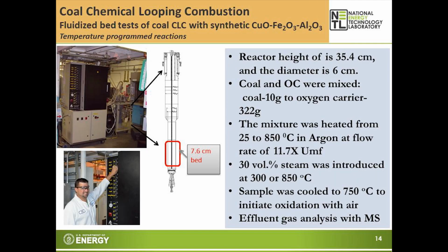We have been also looking at coal chemical looping combustion with the copper, iron, alumina oxygen carrier. We did some bench scale fluidized bed tests to test the coal CLC. Here we mix coal with the oxygen carrier and place it in the reactor, and then do a temperature ramp from ambient to 850 C in argon in the fluid bed reactor. We added 30% steam during the temperature ramp, and we measured the effluent gas composition using a mass spectrometer.